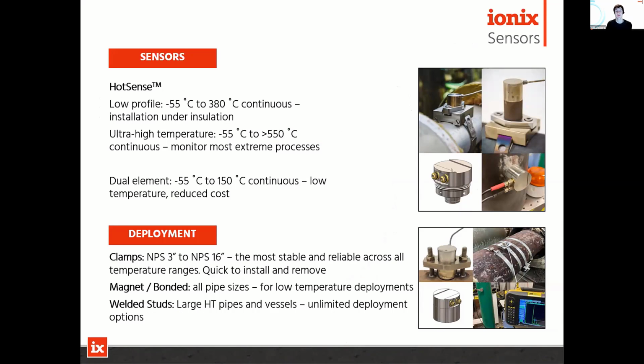So the probes, as I said, we have this 380 low profile probe. We also have a probe which will go up to surface temperatures of 550 degrees C. That's a little bit taller, about 5 inches taller. And we also have a new low profile dual element probe, which is coming out. This will work at temperatures up to 150 degrees C.